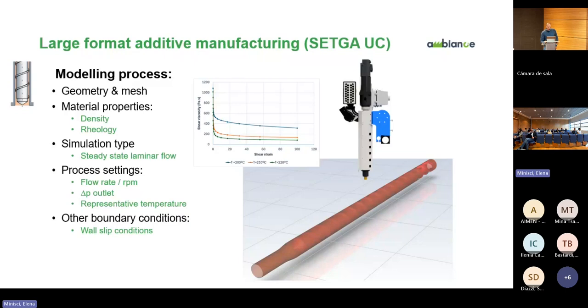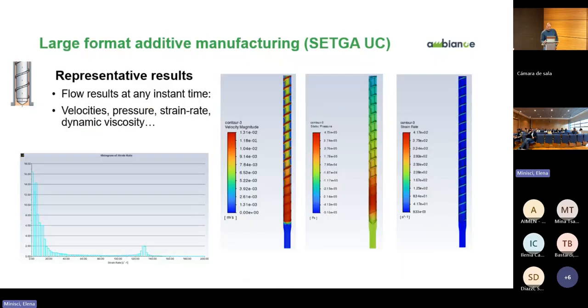Also, we have a condition at the end of the extruder where the nozzle is located. We need to provide several possibilities of incorporating different nozzles of different diameters. That means different resolutions, and also the temperature. The temperature is a representative temperature averaged on the extruder. And here we have typical results of one of these simulations.